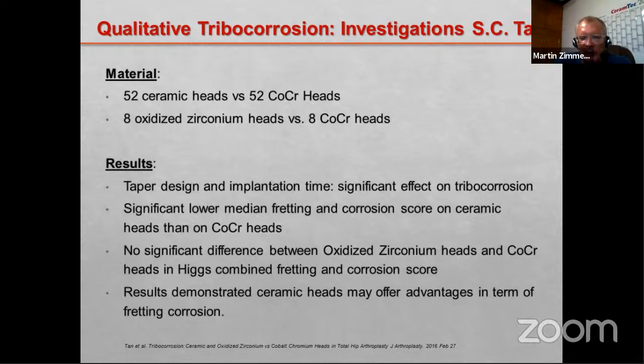Anyway, they came to the conclusion that taper design, specifically taper size and implantation time, has a significant effect on tribocorrosion. That means the longer you have the hip in vivo, the higher the risk of fretting corrosion, and the smaller the taper size, the higher the risk, because you have a higher torque acting on the taper of the stem coming from the ball heads.